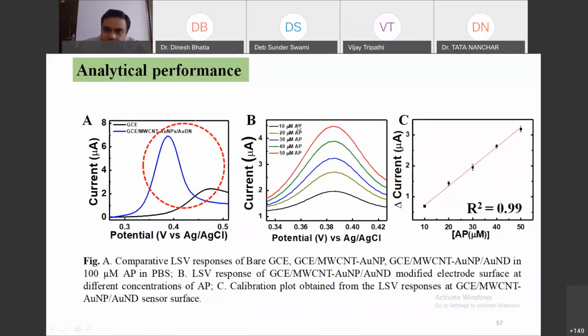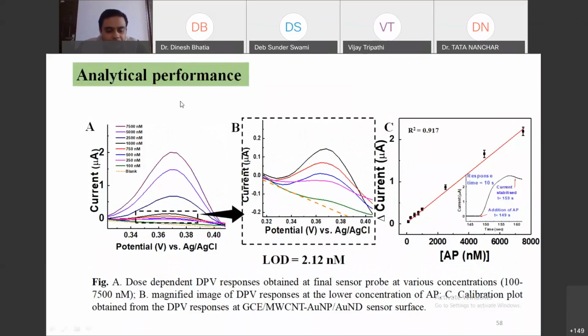We have increased the concentration of acetaminophen from 10 to 50, and there is a straight line which is forming, which is showing a very good correlation between the data. So this is the final calibration where the concentration has been increased from 100 to 7,500, and there is a very clear-cut increase in the signal. You can see from this calibration plot, and the response time is about 10 seconds. I mean, we have done multiple testing. We can say about 8 to 11, 12 seconds. So this response time is basically attributed to the presence of these nanostructures in the matrix. Otherwise, if you remove the nanostructure matrix, there will not be such robustness in the system, right?